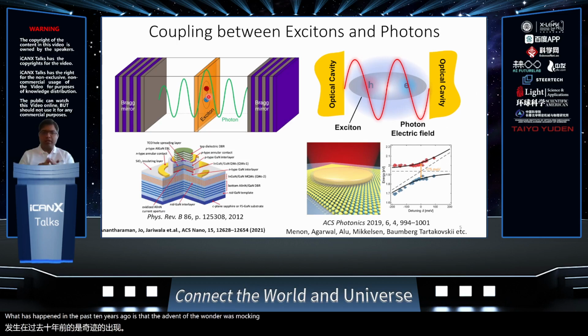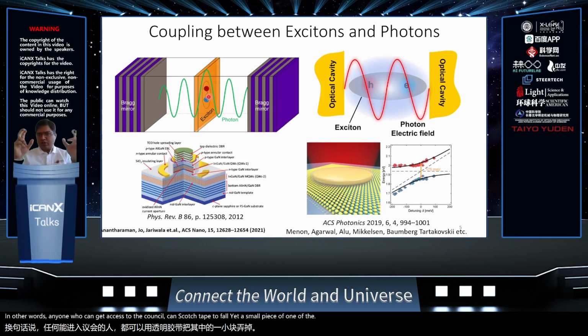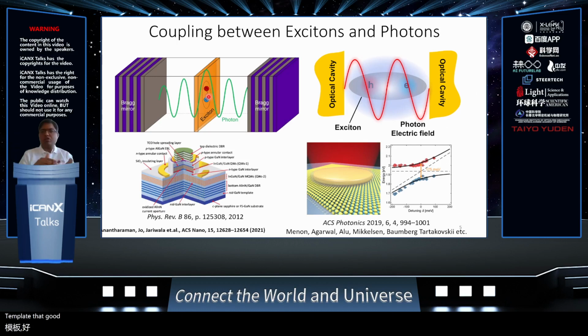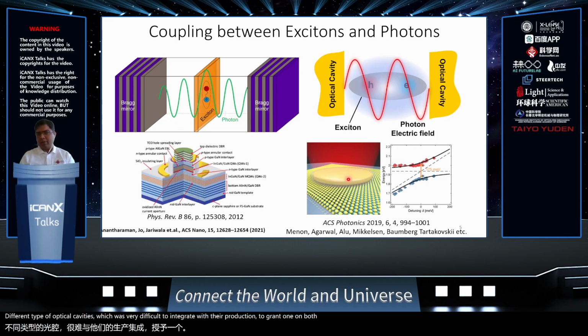What has happened in the past 10 years or so is that with the advent of these van der Waals materials, the field has been democratized. In other words, anyone who can get access to a crystal can scotch tape or exfoliate a small piece of van der Waals quantum well, which is also excitonic, stable at room temperature, and put it onto arbitrary substrates. What this has enabled people to do is combine different types of optical cavities, which were very difficult to integrate with these epitaxially grown quantum wells, namely plasmonic cavities or photonic crystal cavities, and so on. As a result, there has been a large explosion in results in this area.